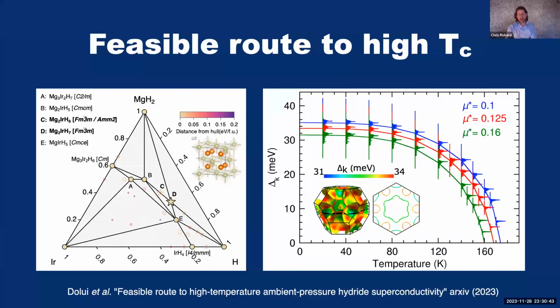Now, to make life easier for ourselves, we constrain the structures to be relatively simple without too many atoms in the unit cell and to exhibit fairly high symmetry. This is based on the observation, at least so far, that most of the high Tc conventional superconductors have exhibited high symmetry. So we use that. That makes the calculations very much more efficient, but it also simplifies our search.